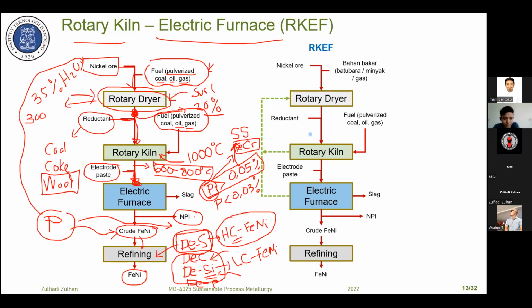We can also charge the ferronickel NPI directly from the electric furnace into the AOD converter, and we can remove sulfur at the end of the AOD process. At the end of the AOD process to produce stainless steel, we add lime, CaO, for sure. First we add silicon, or we add aluminum to reduce the chromium oxide, and then together with ferrosilicon, we add CaO. We add also dololime, and in most cases we add fluorspar, CaF2, and this slag can be used for